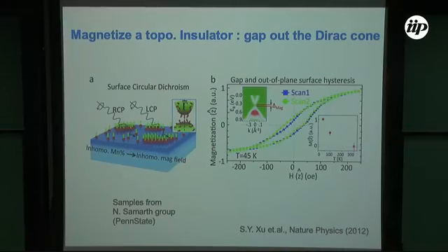The topological insulator Dirac cone we have seen. If you go back to my second slide, I talked about time reversal symmetry. One chiral edge state, then you add another one. That gives you time reversal symmetry, and this is protected by time reversal symmetry. So what happens if we break time reversal symmetry on the surface of a topological insulator? Then the Dirac point is not protected, so you will have a gap. You'll create a massive Dirac fermion, or a gapped Dirac state.